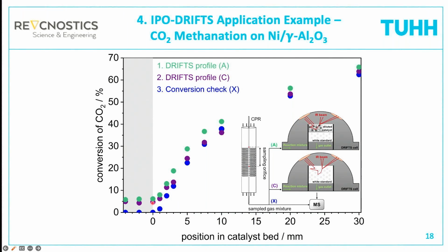As we then drive down the catalyst bed, you see that this contribution gets smaller and smaller because the conversion by the catalyst is, of course, increasing. And if we measure now through the catalyst-filled DRIFTS cell, where we have this highly diluted catalyst, then you see we get an additional contribution, an additional conversion. And in the zone where we have the highest reaction rate, this can be some more percent. So in total, we have here maybe 8% difference, which is not perfect isopotential, but we are approaching this, I would say. This is still acceptable.